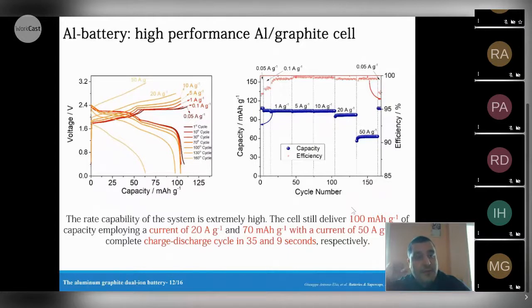From the performance point of view, the fundamental and most interesting characteristic of the aluminum graphite cell is the extremely high rate capability. Here we can see some cycling profiles of an aluminum graphite cell using aluminum as anode and graphite cathode and ethyl methylimidazole as electrolyte. And the active material loading for this test is about 5 milligrams per square centimeter. And the rate capability of the system is extremely high, and we are still able to obtain 70 milliampere hours per gram with a current of 50 ampere per gram of active material. This means a full charge and discharge in 9 seconds. So this kind of system has a performance close to a supercapacitor.